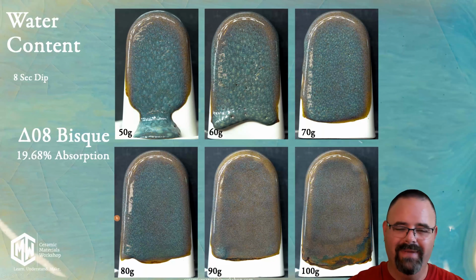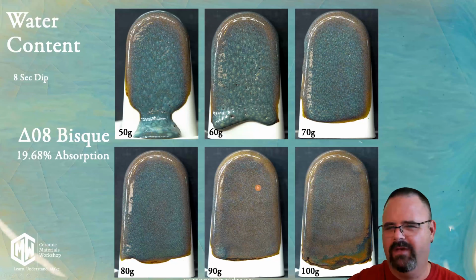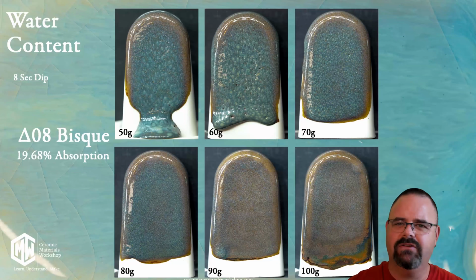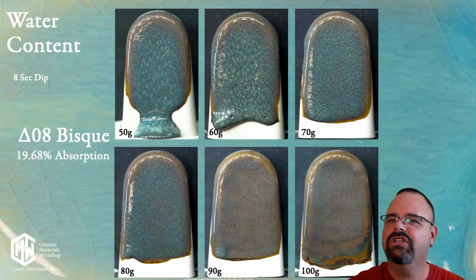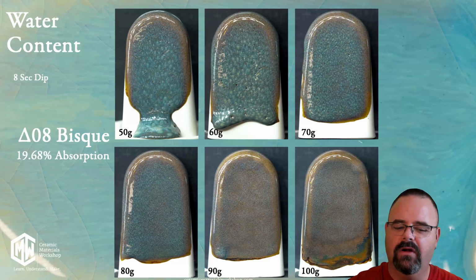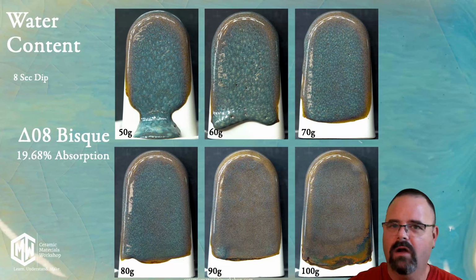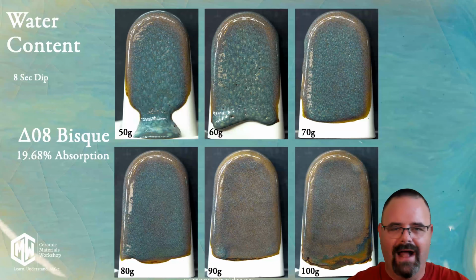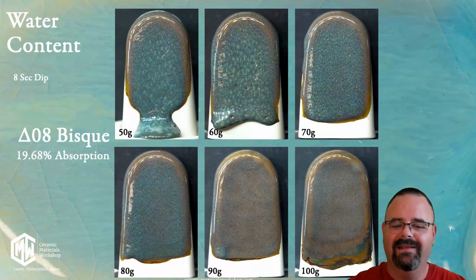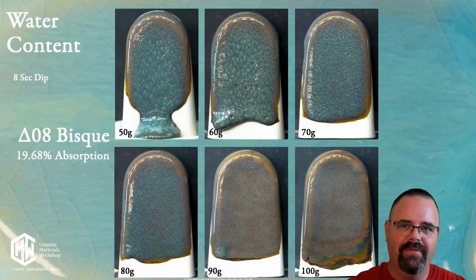With an 08 bisque, because the application doesn't change. You'll often hear people say, oh, well, the glaze is changing because of the application. No, you're literally just not getting enough glaze particles. In this case, the water content is high, so while the bisque is absorbing water, it doesn't have as many glaze particles coming with it, so the glaze application ends up thin.